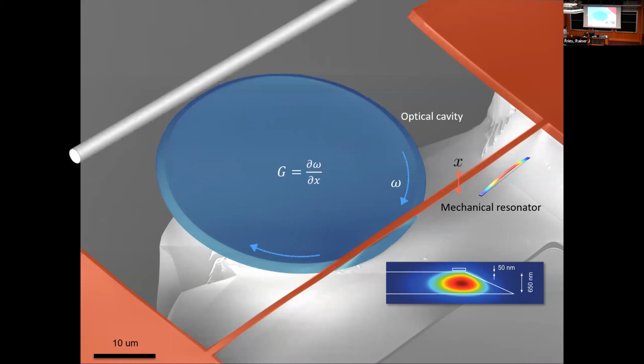How do we do that? Well, whenever the mechanical resonator moves, it shifts the cavity resonance frequency because you're changing the local dielectric index of refraction. And you can measure that frequency shift by taking an optical fiber, pumping some light in the cavity, it circulates around, it comes out and gets a phase shift. You can measure that phase shift using standard interferometric techniques.